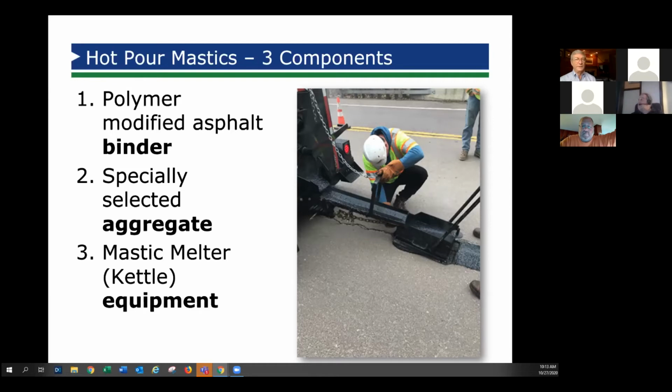It's called tensile adhesion. And that is one of the things that is really positive about this, because unlike other repair materials, this is really the only waterproof repair. So the performance level on this tends to be very long. There are manufacturers that are engineering these products for a 1 to 3 year longevity, and then there are some who are going 8 to 10. We can do a lot of things with this because, number one, it is waterproof. Number two, the aggregates in there are giving us structural strength back into the pavement. We're filling that void with a load-bearing material.